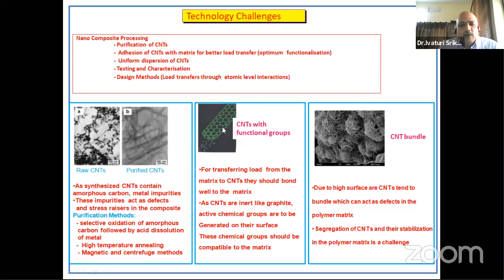Then, as I told, nanotubes have very high strength, but they don't bond well with other materials. Those who are familiar with organic chemistry may know about the functional group, the group that reacts with other molecules. It is not the long chain. You can consider the nanotube as a long chain of carbon. Without a functional group, it will not bond with any matrix. Unless there is a bond between the binder and the reinforcement, you cannot translate the reinforcement strength to the composite. So for that, you need to generate some active functional groups on it.